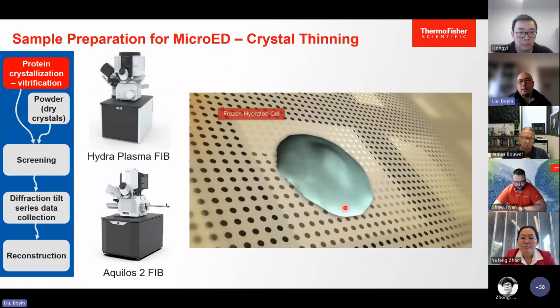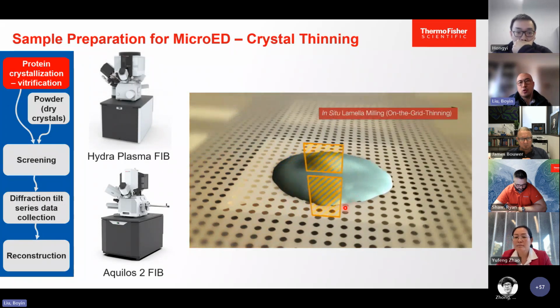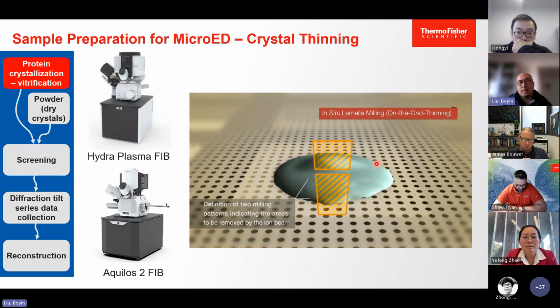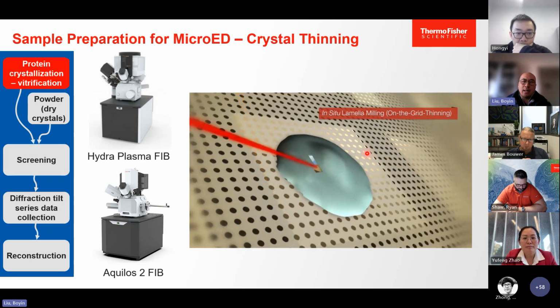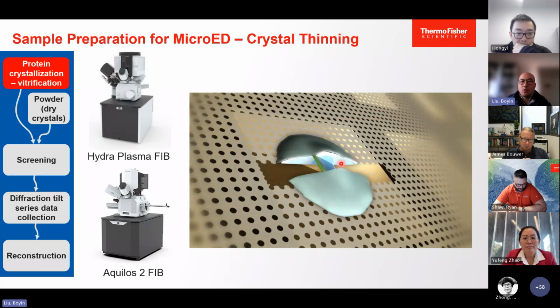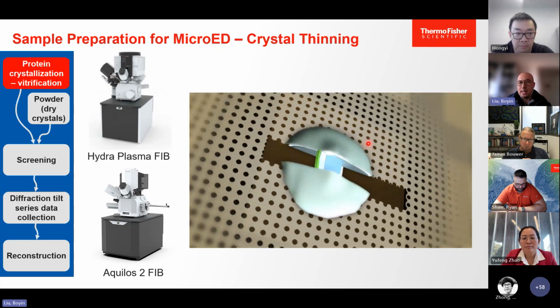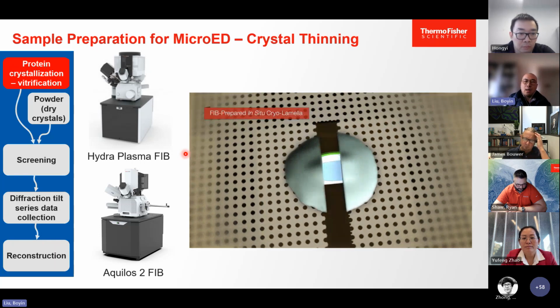And then, for example, if this is a crystal, you move to a milling angle, usually about 10 to 20 degrees, and set up two milling windows with the lamella in between. Then you gradually do rough milling and fine milling, using smaller and smaller beam currents to create a very good lamella. So the procedure is exactly the same as cryotomography.